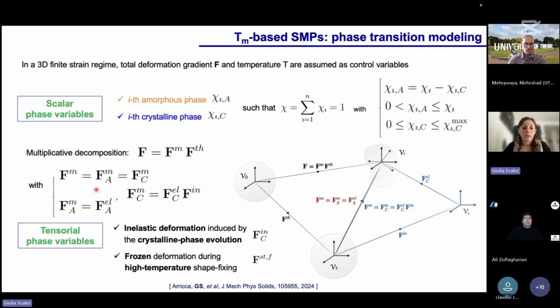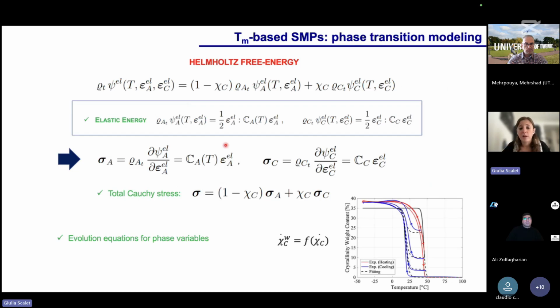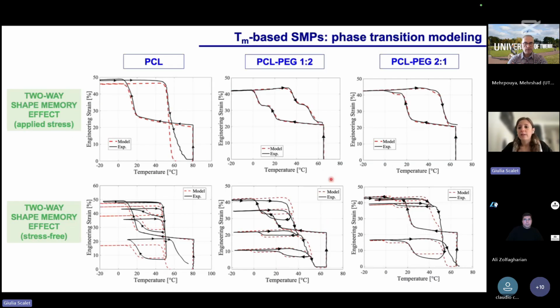So again, we introduce phase variables, scalar and tensorial, and we derive again, as I described before, all the constitutive equations and the evolution law for the phase variable, in particular using the experimental evidence we observed. So it is a purely phenomenological model. And the results are very, very good, in the sense that we validated the model for different types of network, both on homopolymers and copolymer networks, also for different ratios between the polymers. So the model is able to catch well, despite this very complex behavior, the material's shape memory performance.